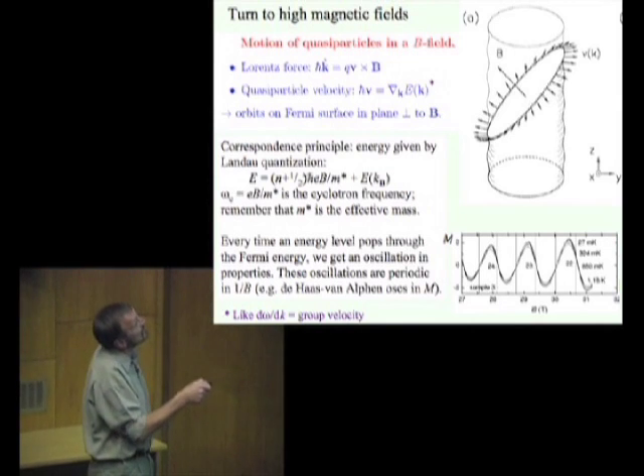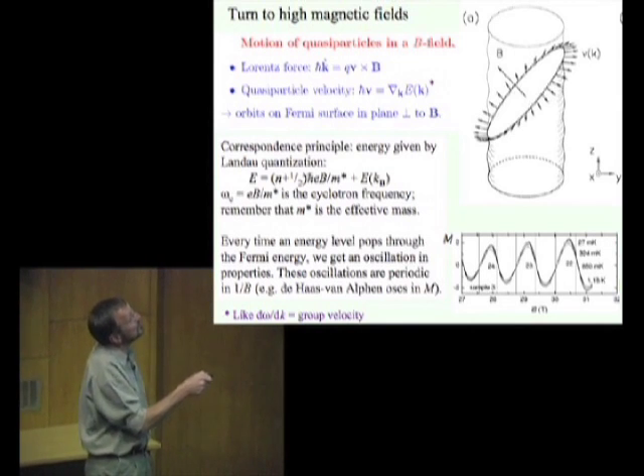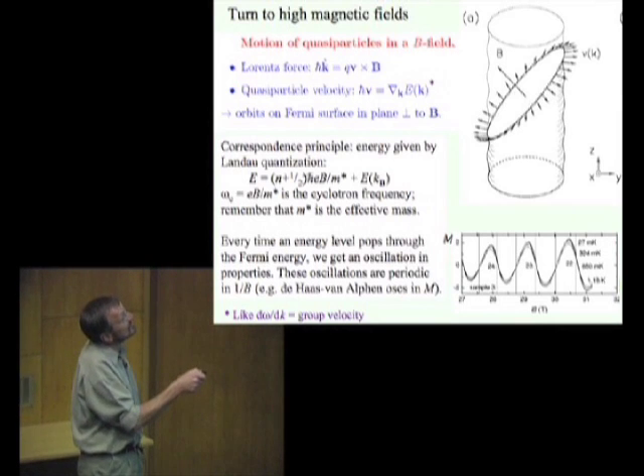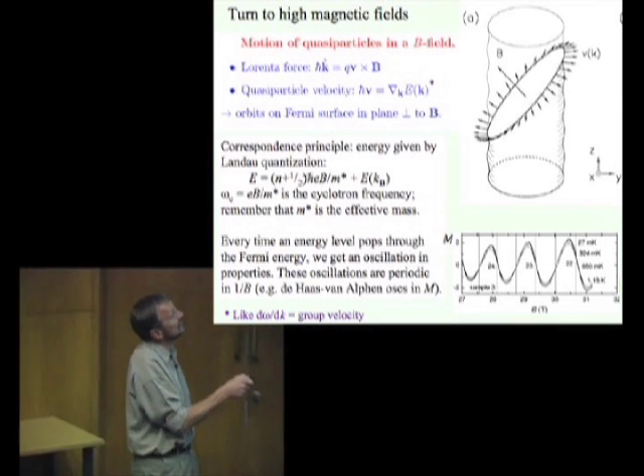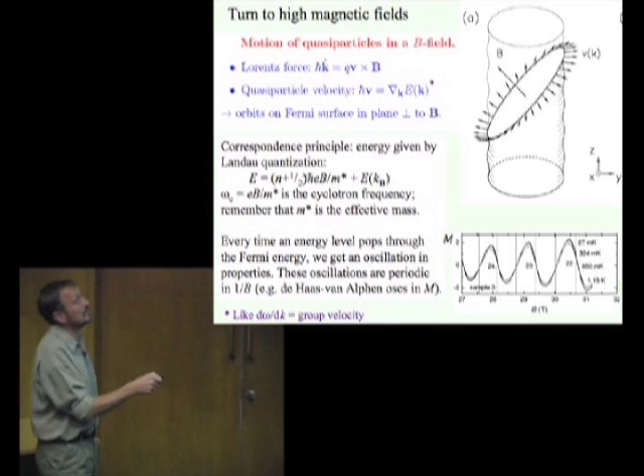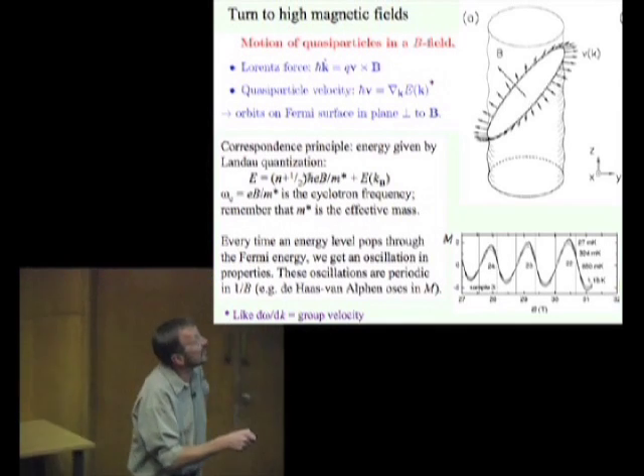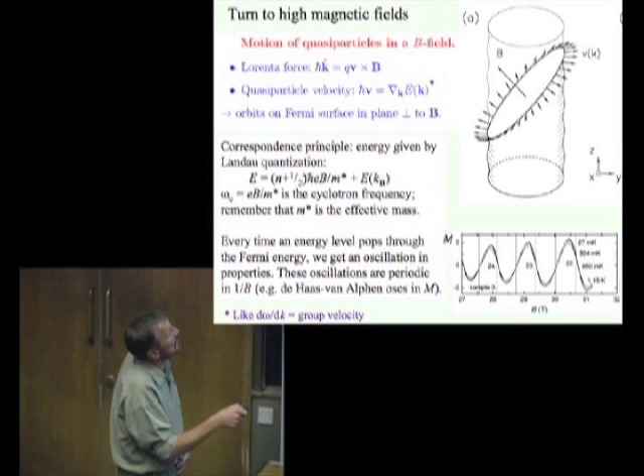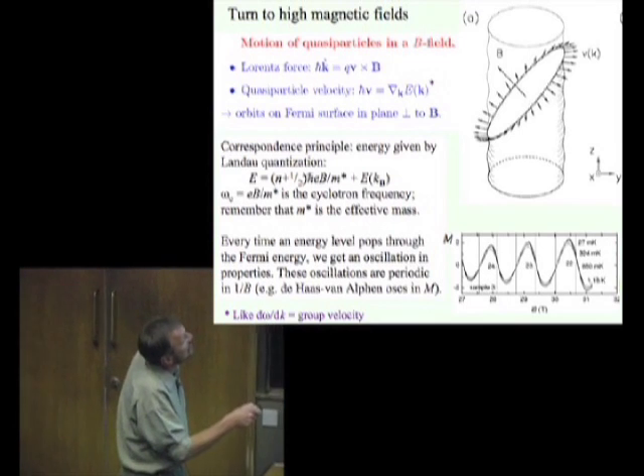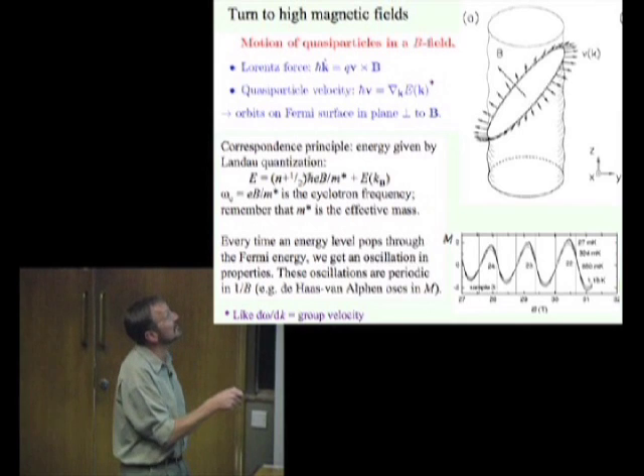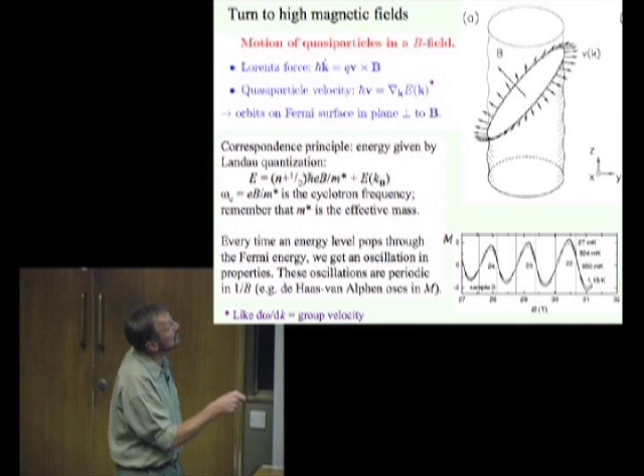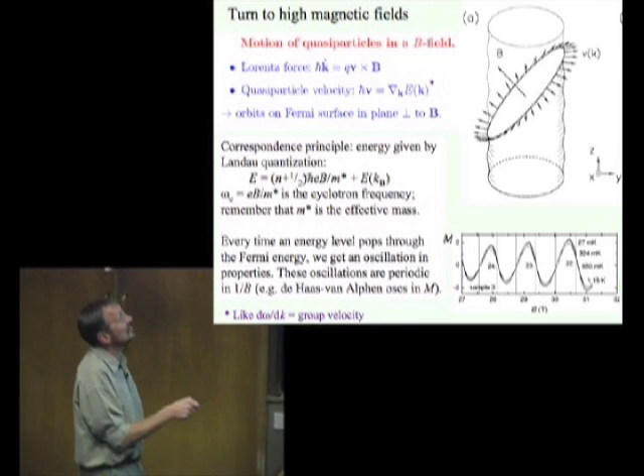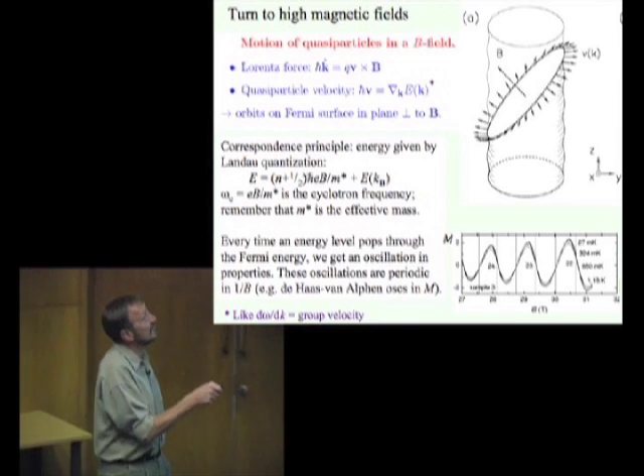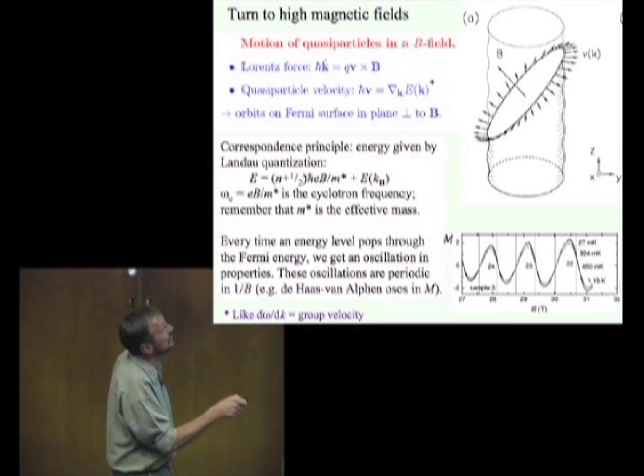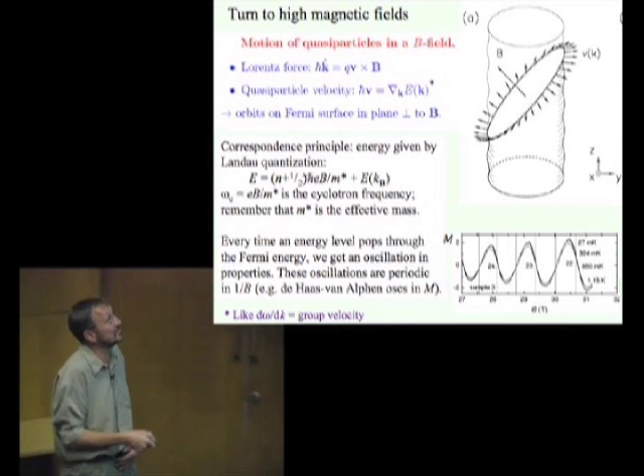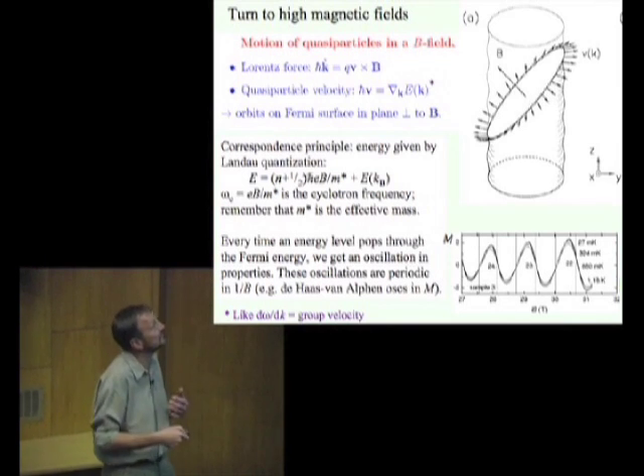So what you can see is that this change is going to be perpendicular to the velocity, and it's going to be perpendicular to the magnetic field. But also, the velocity is perpendicular to the Fermi surface. So if we have a quasi-two-dimensional Fermi surface like this one, and we apply a magnetic field in a certain direction, what we're going to get is an orbit on the surface of constant energy in a direction which is perpendicular to the velocity and perpendicular to the magnetic field. So it's going to give you a cross-section of the Fermi surface in a plane perpendicular to the magnetic field.